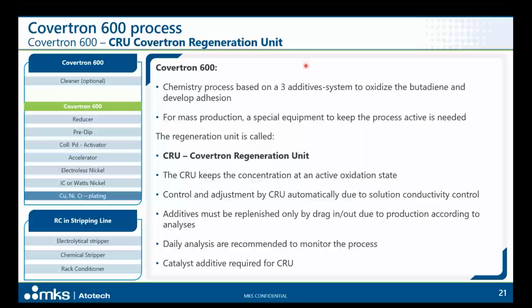What we need to mention is that from these 3 additive systems, 2, as mentioned, are responsible for developing the right etching pattern, and the last one is a specific catalyst that is required to optimize the electrolytic reoxidation reaction in the CRU unit. In terms of rack conditioning, as mentioned before, in the stripping line we can install rack conditioning to prevent rack metallization. The regular process sequence will be electrolytic stripping of the tips, chemical stripping, and finally the rack conditioner, before the racks are sent back to the line for racking the parts.